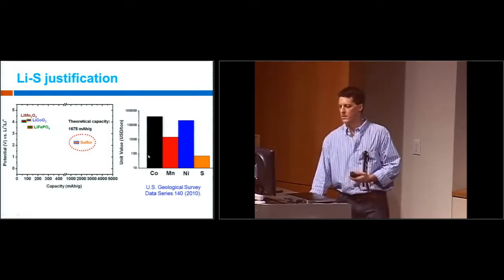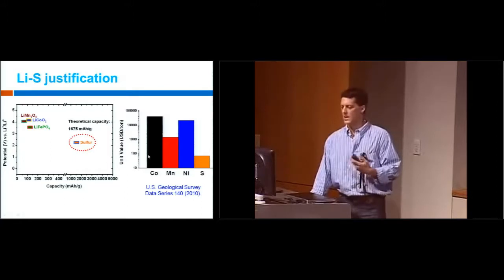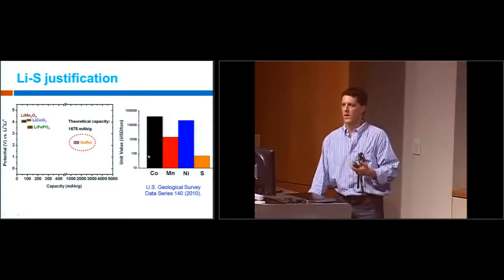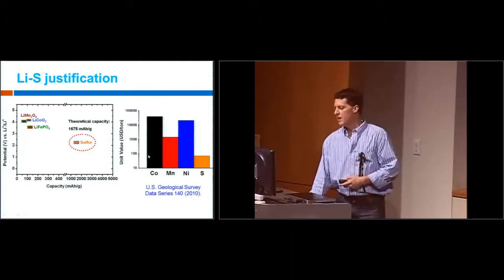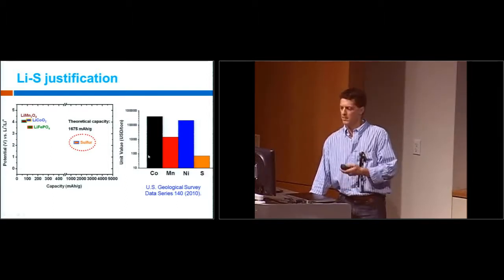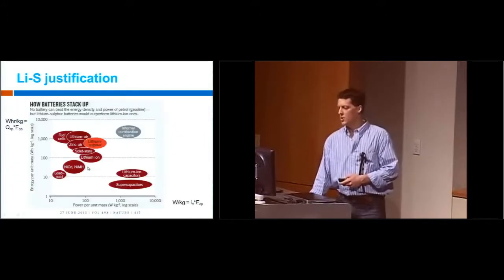Now you'll also notice that the operating voltage of the sulfur battery is about half that of the oxide, which means that the true advantage is not 10 times as much capacity; in terms of energy, you get about 5 times as much energy out of these. The other thing I want to call attention to is the cost involved. Sulfur is extremely cheap compared to the transition metals that are the basis for the current oxide materials. This graph shows the gravimetric power density and the energy density, and you can see that in terms of what's available today, lithium-sulfur batteries are about the closest thing we have to the internal combustion engine in terms of energy supply.